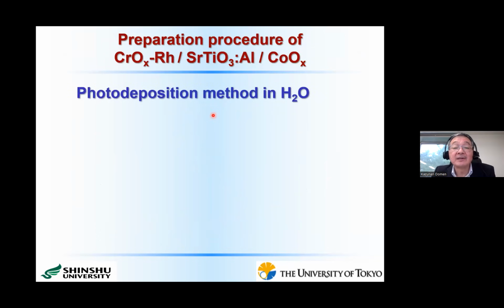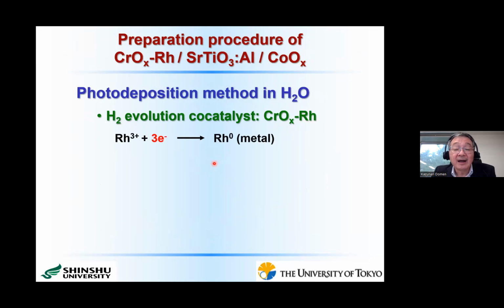As I said, all the metallic components of the co-catalyst are photodeposited in an aqueous solution. At first, we construct the hydrogen evolution co-catalyst. That is a rhodium-chromium coaxial structure. In this case, we first deposit the metallic rhodium nanoparticles by using photoexcited electrons to reduce rhodium 3+ into rhodium 0, rhodium metal.